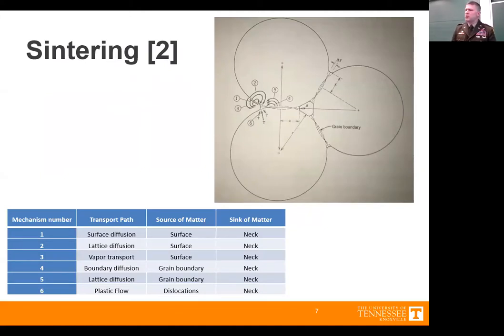So again, not to belabor this too much, but in general, sintering is a mass transport. You can see from the slide there are at least 6 different mechanisms. Not all of them are necessarily applicable. Plastic flow specifically usually is only associated with the sintering of metals or glass powders. When you're talking polycrystalline ceramics, you're really only talking about those first 5, so surface diffusion through lattice diffusion. But essentially, during heat treatment, mass is moved from either the boundaries between particles or the interior of particles, and it moves to the joining surface between where those 2 particles or 3 particles touch, and necks are formed. So matter is moving from one place to another, and that's how those pores are eliminated and densification happens.